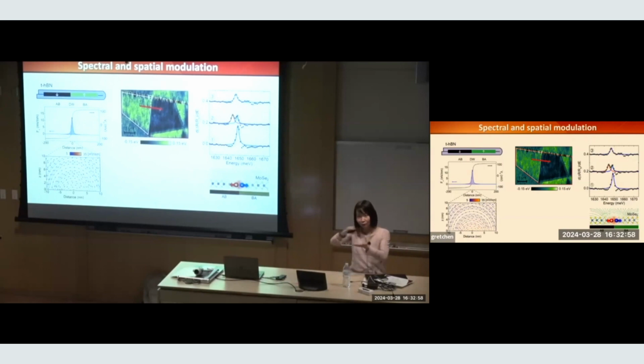An in-plane electrical field would act on positive charge and negative charge in opposite directions. And I can really see that. This is a large domain intentionally. I take the optical spectrum within each domain, and they only give me one exciton resonance. But if I take a spectrum overlapping with a domain wall, I actually have an additional resonance. That resonance is shifted by the Stark shift.